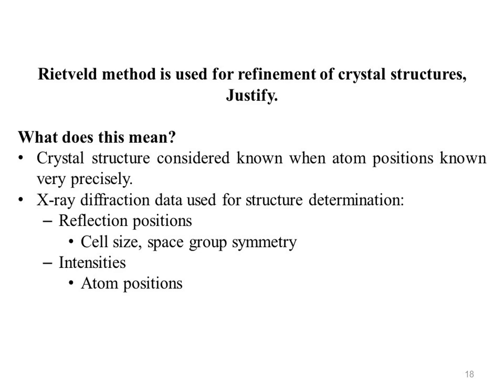Reflection position, cell size, space group symmetry, intensities, atom positions. Thus precise lattice parameters and precise atom positions are determined in two separate steps. Initial values of atom position obtained using structure analysis are rarely the most precise values and closest to truth. Values must be refined. Use least square procedure to make small adjustments in atom position.